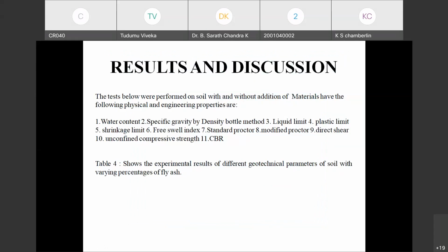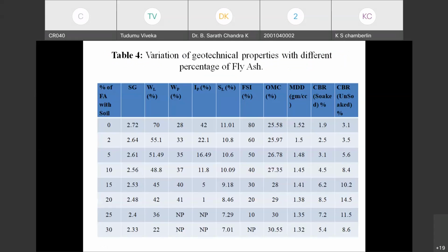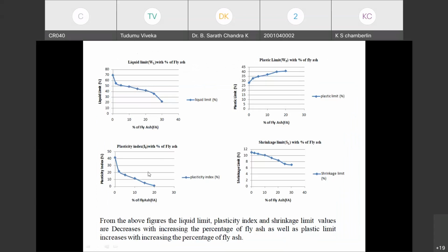And next one is results and discussion. These are some of the tests I followed. Table 4 shows the experimental geotechnical properties of the soil plus fly ash: specific gravity, liquid limit, plastic limit, plasticity index, FSI, OMC, MDD, and CBR soaked and unsoaked values. These are the graphs from the table. From the above figures, the liquid limit, plasticity index, and shrinkage limit values decrease with the increase in the percentage of fly ash, while the plastic limit increases with increasing percentage of fly ash.